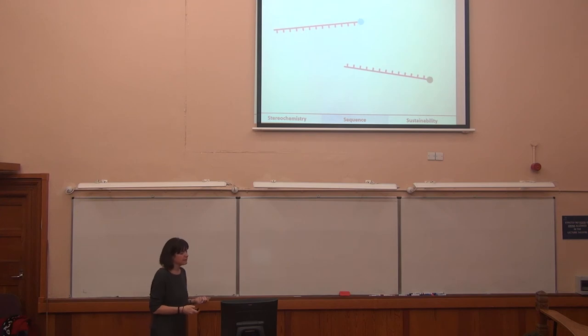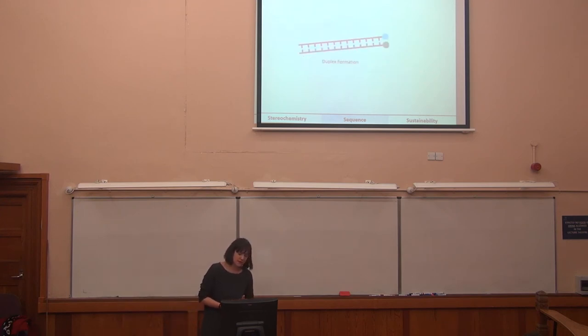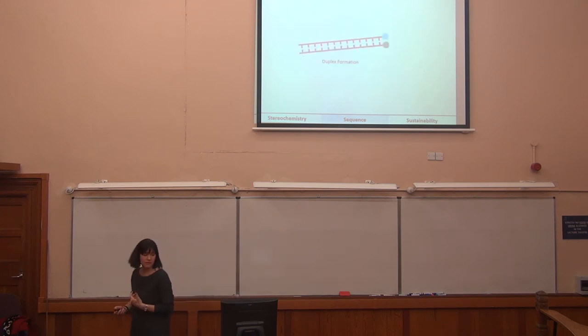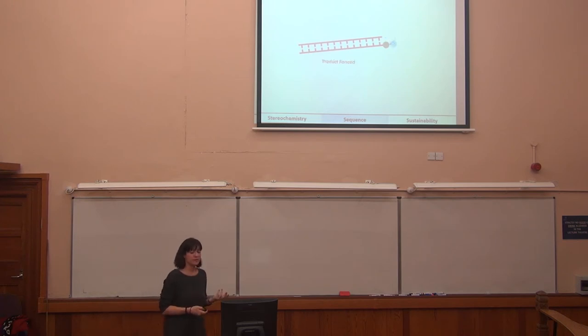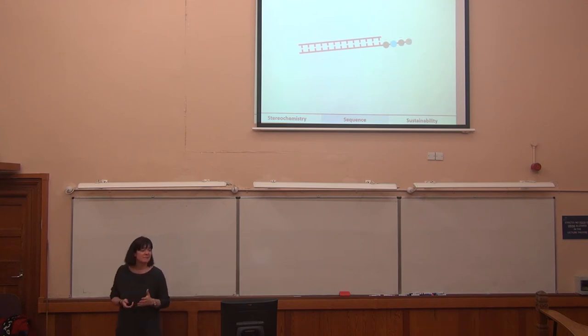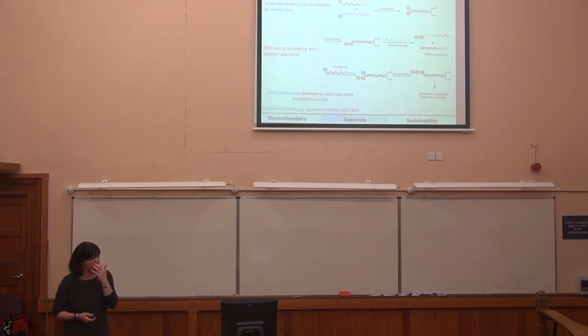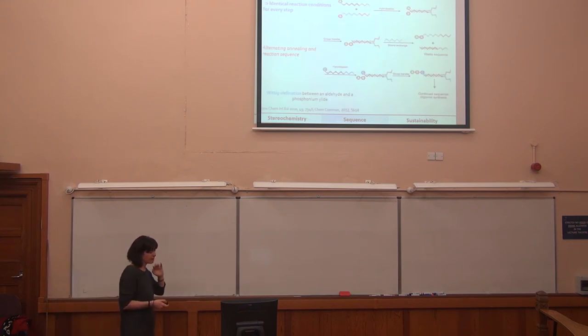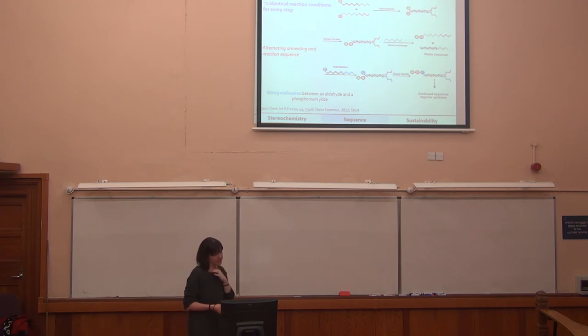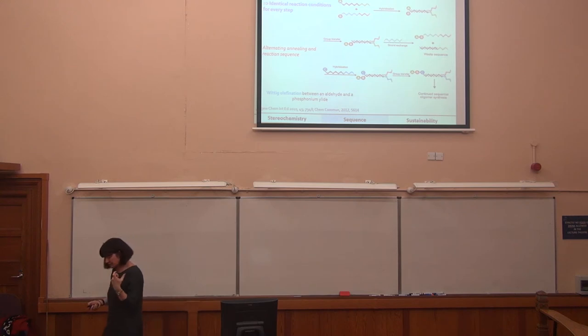Now, to show that very simply, if you imagine you have two reactive groups and two complementary DNA strands, you form a duplex, you bring your reactive groups into very high local concentration, you can hopefully do a transfer reaction, form a product, and you can keep doing that and build up your oligomer. It's obviously not that simple. One of the first things we did was look at forming this strand exchange mechanism. And one of the key things we had to look at was trying to get identical reaction conditions in each step so we would be able to reach relatively long oligomers.